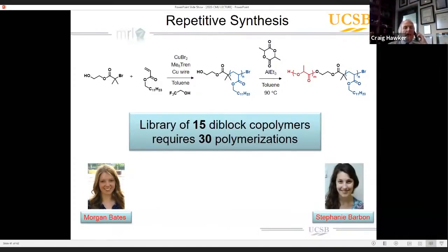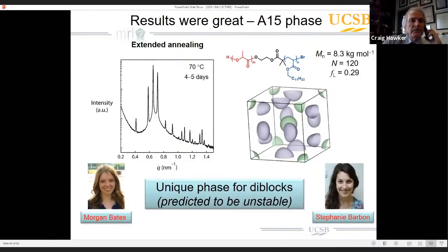Using these techniques, it was a couple of months of work, but what Morgan and Stephanie were able to do was to make well-defined materials. They had a library of about 15 diblock copolymers, and when you work it out, that's around about 30 polymerizations, 30 purification steps. So it's a bit of a challenge, but they were able to make all of these different materials to start looking at the morphology of these diblock copolymers. And lo and behold, because they had prepared enough samples with enough range, they were able to find this unique A15 phase, which has been predicted to be unstable for diblock copolymers.